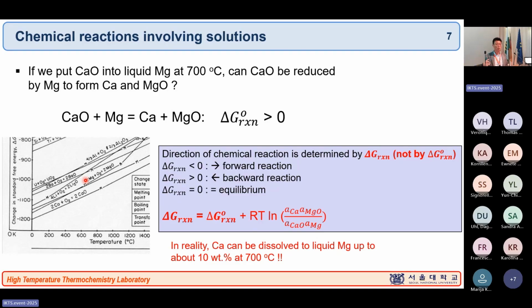But if they are making a solution phase, their activity may not be 1, typically less than 1. And depending on that, this reaction can go forward. So in reality, at 700 degrees Celsius, believe it or not, you can make up to about 10% of calcium dissolve into the magnesium, driving this chemical reaction forward until the calcium reaches about 10% in the magnesium liquid.